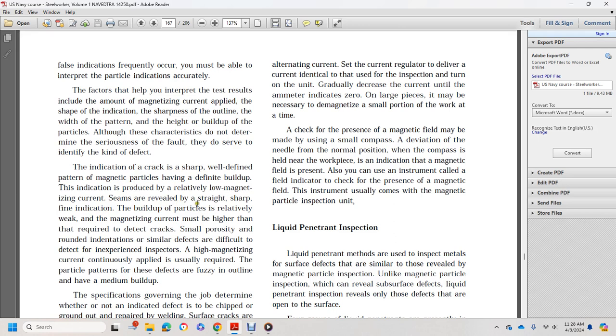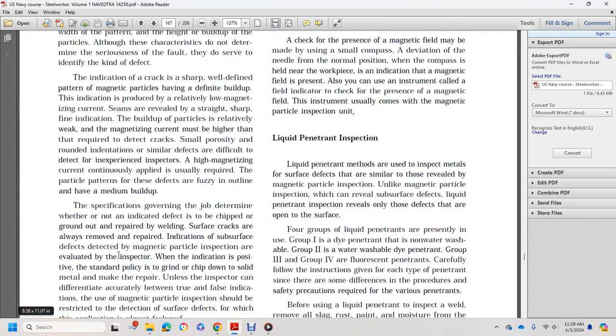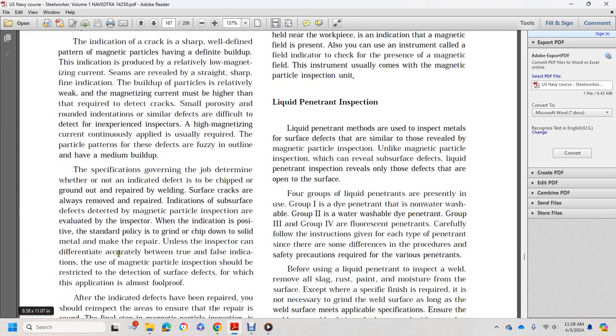The indication builds up particles relatively weakly, and the magnetizing current must be higher than that required to detect cracks. Small porosity, round indentations, or similar defects are difficult to detect for an inexperienced inspector. A high magnetizing current, continuously applied, is usually required to position the particles. These defects are fuzzy in outline with medium buildup.